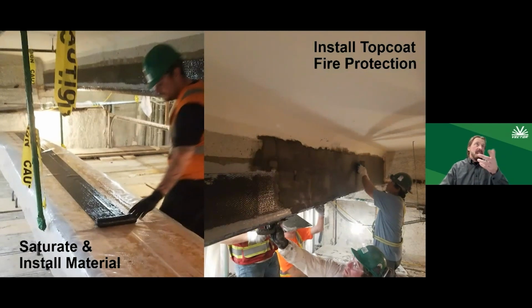So you can see the layup table. The technician on the left is saturating the resin, getting it ready for installation. And then on the right, you can see on the seams, they've detailed the edges of the carbon fiber fabric with a paste epoxy. That's just to ensure that the edges are tightly adhered to the concrete using a paste epoxy.